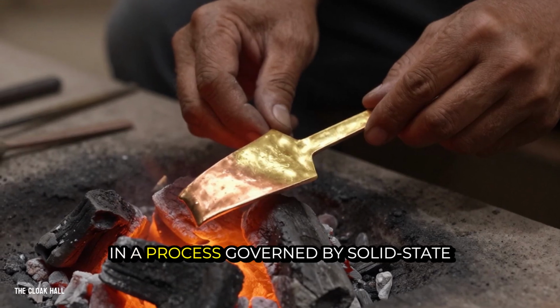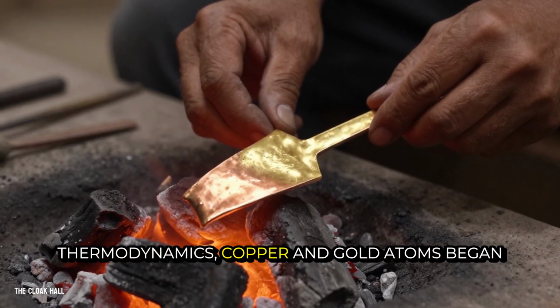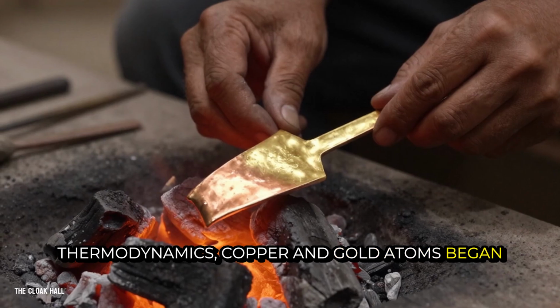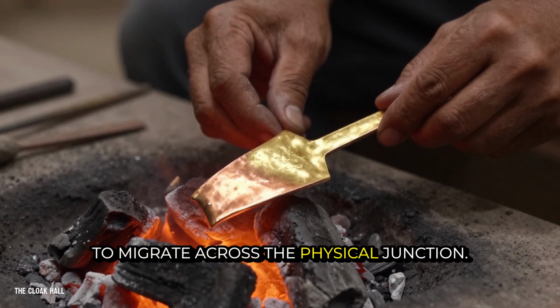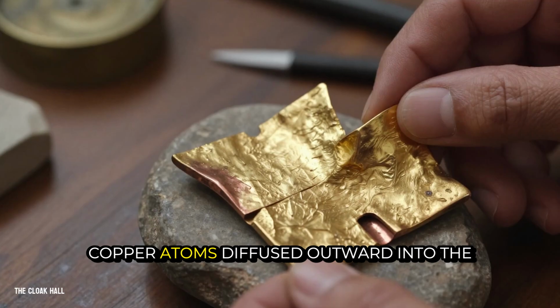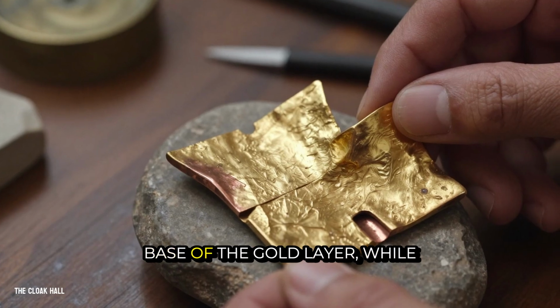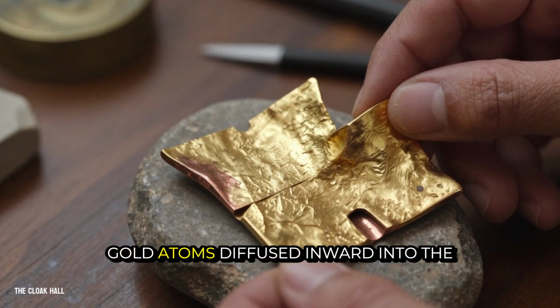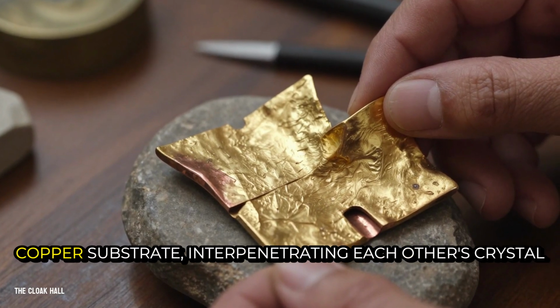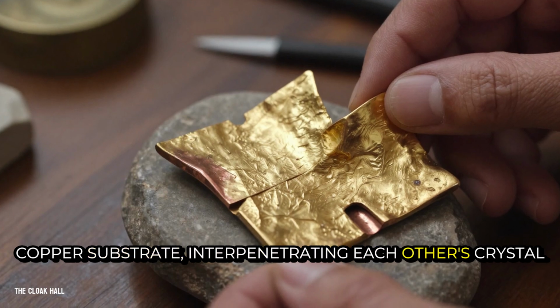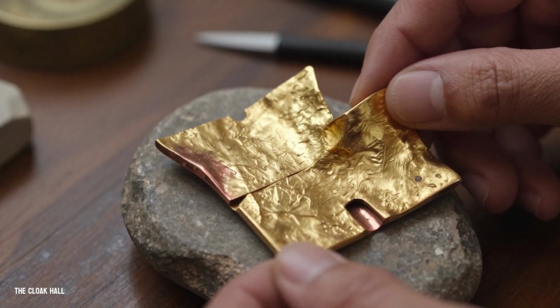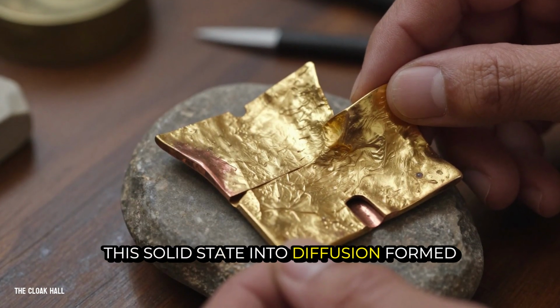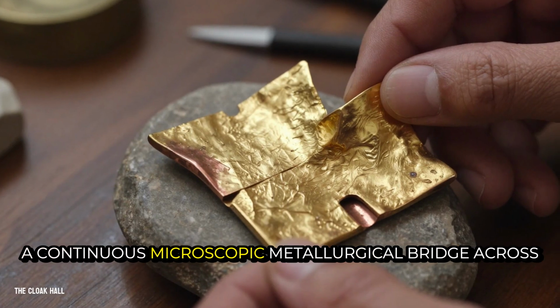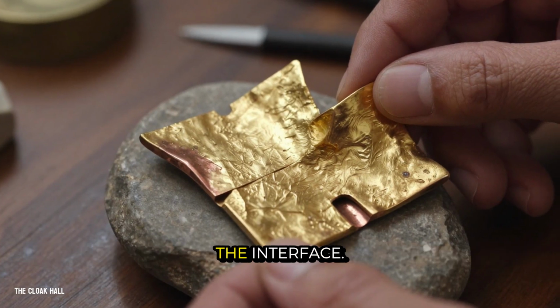In a process governed by solid-state thermodynamics, copper and gold atoms began to migrate across the physical junction. Copper atoms diffused outward into the base of the gold layer, while gold atoms diffused inward into the copper substrate, interpenetrating each other's crystal structures. This solid-state interdiffusion formed a continuous, microscopic metallurgical bridge across the interface.